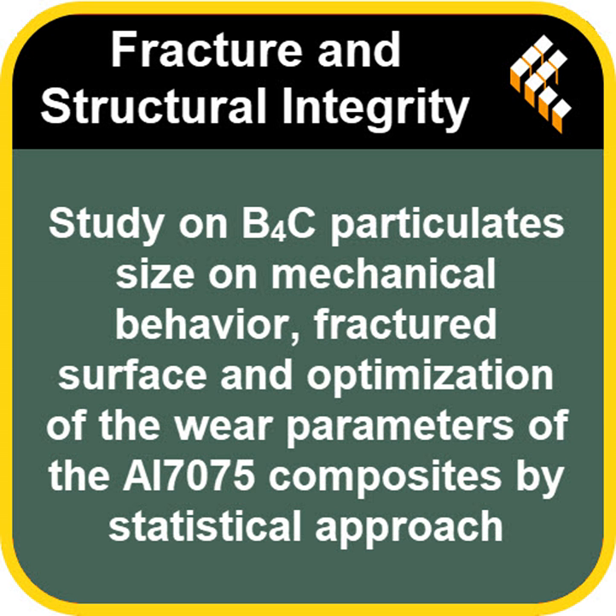And the microparticles? They led to larger surface roughness, partly because they don't disperse as evenly, which can weaken the bonding at the interface. And the larger hard particles themselves create bumps and act like abrasive points. Did that difference hold up after the wear tests? Generally, yes. After wear, the nano-reinforced MMCs often stayed smoother, especially if the sliding distance and speed weren't too extreme. The microcomposites, though, often showed a big increase in roughness after wear. You'd see pits and little craters where particles had been dragged out or fractured.